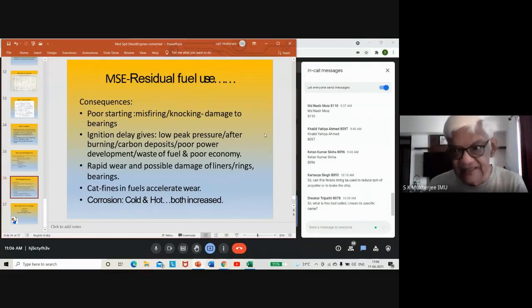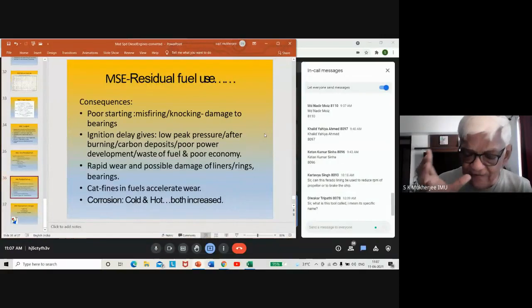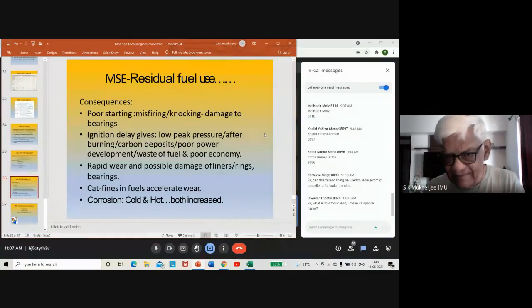But hot corrosion can still be there because the quantity of vanadium has still not been reduced much. And the amount of sodium that comes from seawater is variable. So if the proportion of sodium to vanadium is 1:3, then the catalytic effect of formation of salts is multiplied. And these salts, there are 8 in number. They're called vanadates. Sodium divanadate, trivanadate, all the vanadates are there. And they are the main cause for hot corrosion.